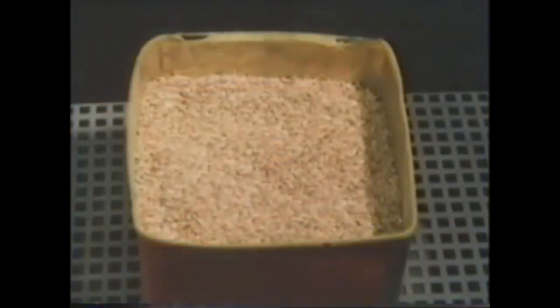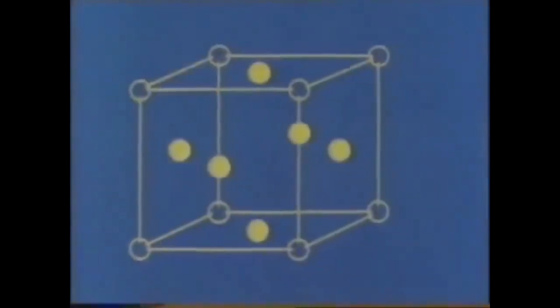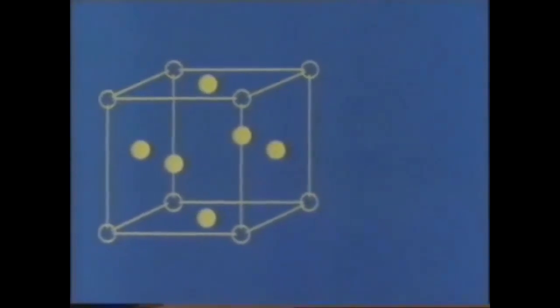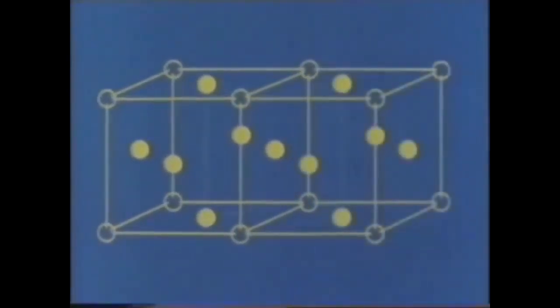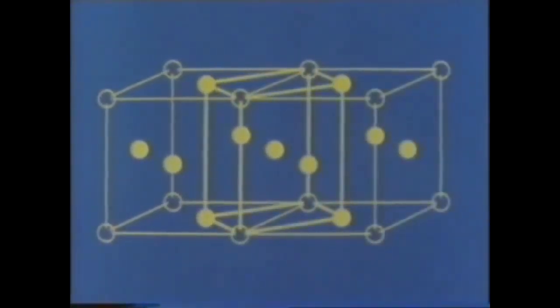Now, instead of cooling slowly, if the rod is cooled rapidly by quenching in water, the carbon atoms have no time in which to come out of the solid solution. The resultant structure can be explained by considering two face-centered cubic arrangements. As the metal cools, it can only revert to a distorted body-centered cubic arrangement due to the enforced presence of the carbon atoms. The structure is known as martensite.